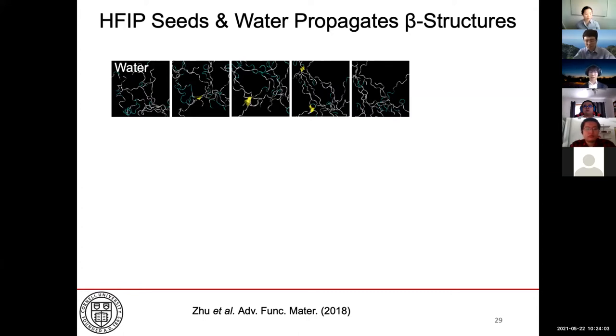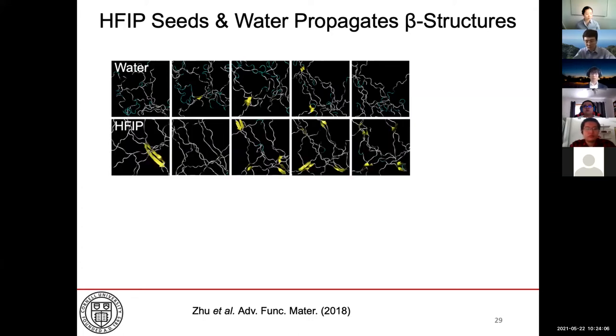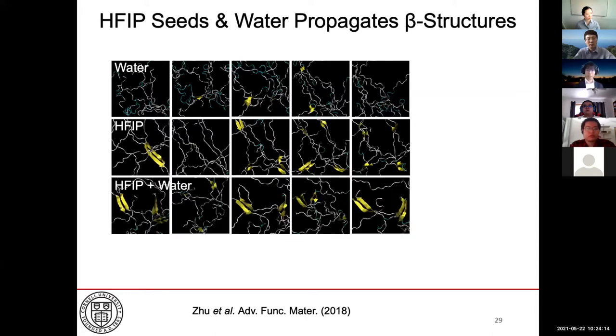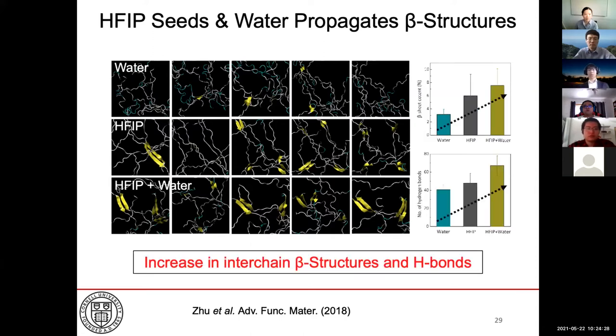And they form amorphous structures. And on the other hand, solvation in HFIP actually prevents hydrophobic aggregation, but it also seeds certain small amounts of beta structures in the random network. And if we further add water to this metastable state, it will drive the system towards gelation, very similar in effect to amyloid fibrillation by perturbing saturated protein solutions. And then we can see a concomitant increase in beta sheets and interchain hydrogen bonding.